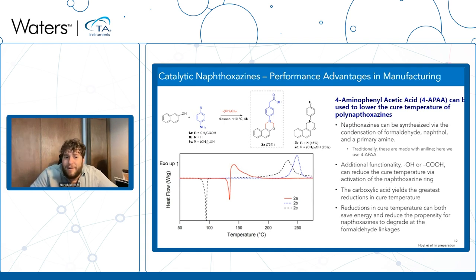When we make our bio-derived, so this little 2A, which is shown in the red line, naphthoxazine resin, what we can see is you heat up this material, it goes through a melting transition, and then immediately after that melting transition, it will go through an exotherm and it will cure, and this material from the bio-derived resource will complete its cure before the petrochemical derived material has even started its cure, which is really awesome, right?